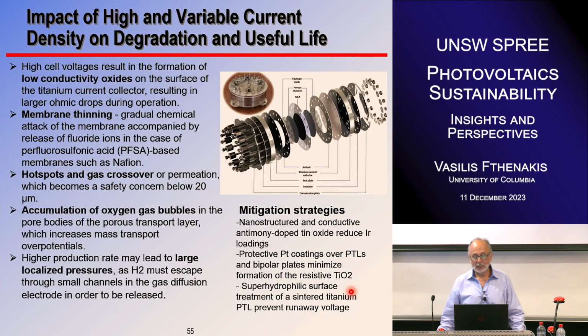People are looking into strategies like nanostructured and conductive oxides that can reduce the iridium loadings, protective platinum coatings, and bipolar plates with super hydrophilic surface treatment of the titanium PTL that prevent runaway voltages. There are some mitigation strategies, but those are not developed yet. There is at least one company that I know, Nel Hydrogen, Netherlands-based, but it also has a production facility in the US. They say they have prototypes that work at high current density, but we don't have a commercial product out yet.